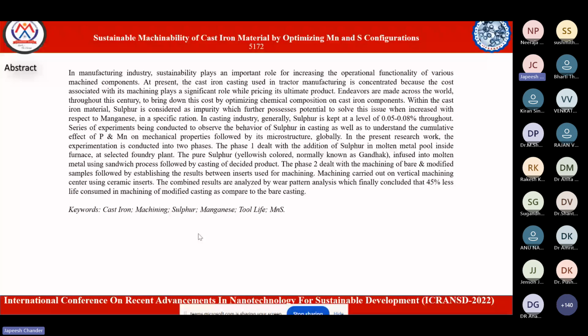We have added sulfur into cast iron FG260. People from the chemical industry or from chemistry by background might know that sulfur is always considered as an impurity in the metals, but we use sulfur and we harness different benefits from this. We increase sulfur. Normally in the market, if you see FG260 casting, the sulfur is only in the range of 0.05 to 0.08% throughout the industry if you search. We just try to increase the percentage of sulfur.